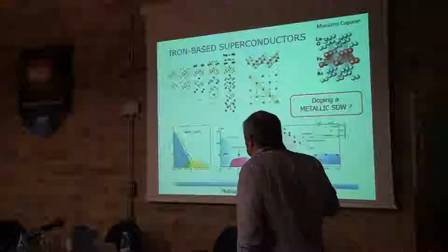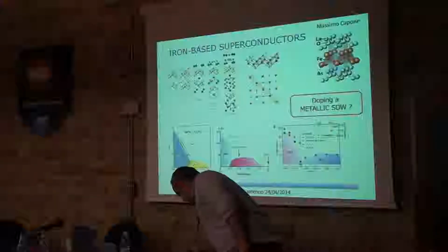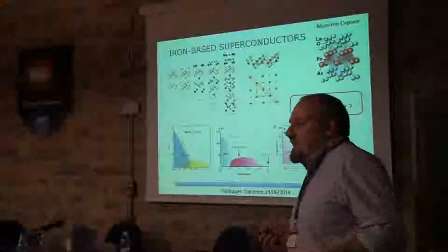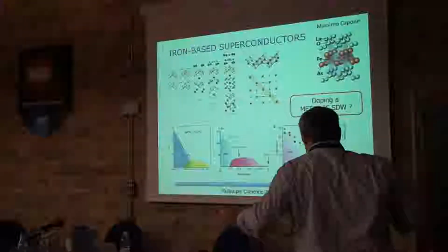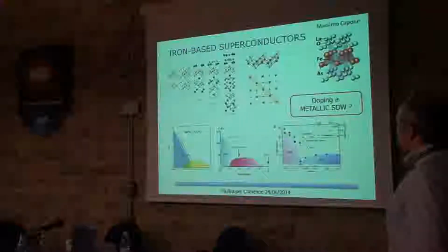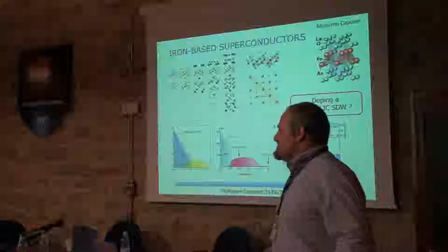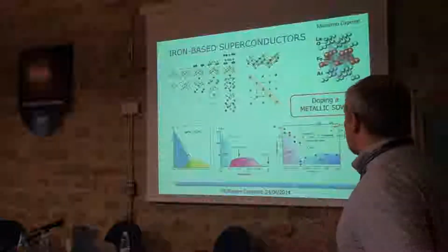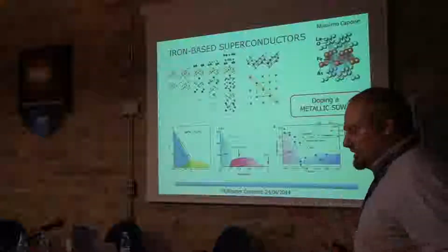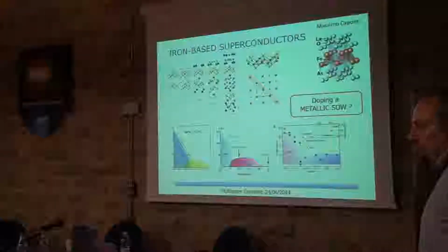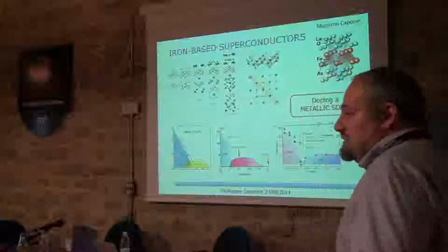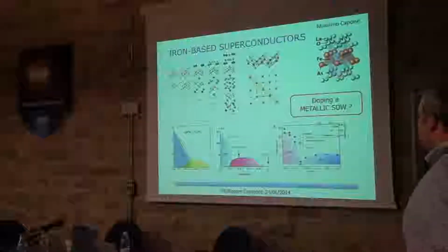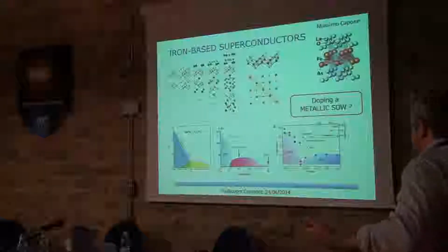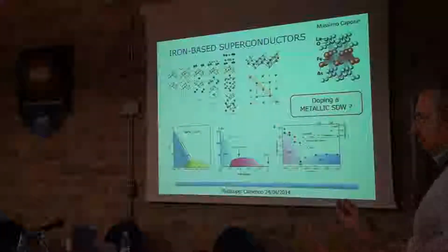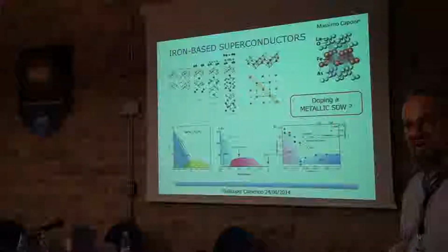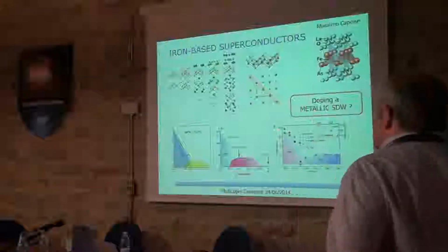So, this is for the cuprates, and essentially people have learned to believe this story. So now let's come to the iron-based superconductors. Of course, I don't need to make an introduction because several speakers did it in some detail. We have a bunch of materials which all share these iron something layers, mainly pnictogen but also chalcogen. They share some structural chemical analogy with the cuprates, and somehow they share a phase diagram that, at least at first glance, may look similar to that of the cuprates. We have some magnetic state, which here is a metallic spin density wave, which turns into a superconductor when we dope. As we've learned from previous speakers, different stories happen in the different subfamilies of this family, but still there is this overall thing.